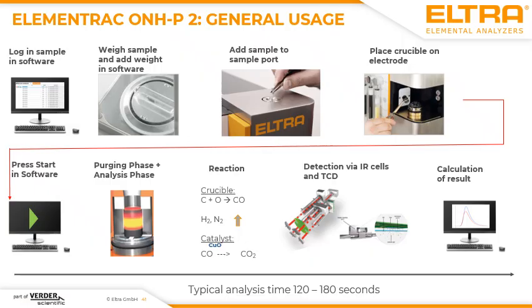When you apply the sample to the sample port, you also have to think differently when you analyze powders in contrast to analyzing solid samples, because for powders usually a capsule is always required. Placing the crucible on the electrode and starting the analysis is more or less not affected by the kind of powder. So I would say the rest of the analysis process is not affected by the shape of the sample.